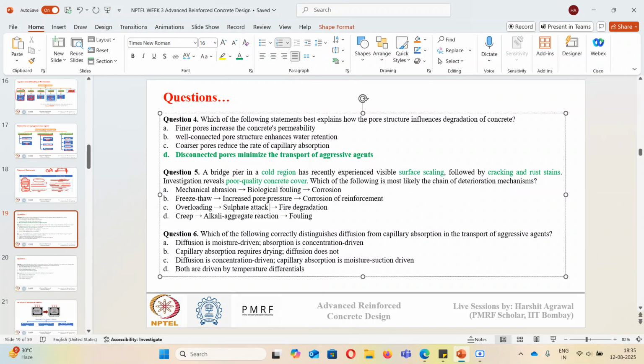How it is increasing the pressure, we'll talk later. So due to this freeze and thaw, cracking would have occurred in concrete, which could have led to easy ingress of ions through concrete, and this resulted in corrosion of reinforcement. So that's why we have cracking and then rust stains also. So this can be a likely chain of degradation mechanism. Cracking led to easier ingress of ions, which led to corrosion of reinforcement.